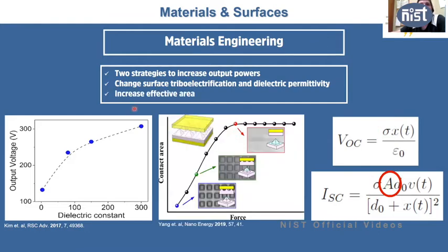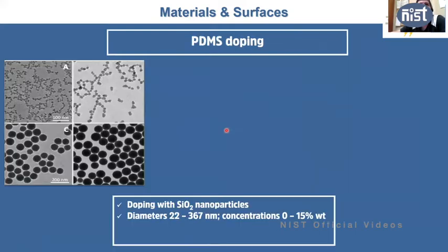The second is that you can increase the effective area. So you can see here, for example, the short circuit current depends linearly on the area. And here is an example where you can change the contact area by just changing the pressure or the force that you apply on these nanopyramid-like structures, and you get an increase of the contact area by the increase of the force, which relates to an increase of the power that you get from your devices.